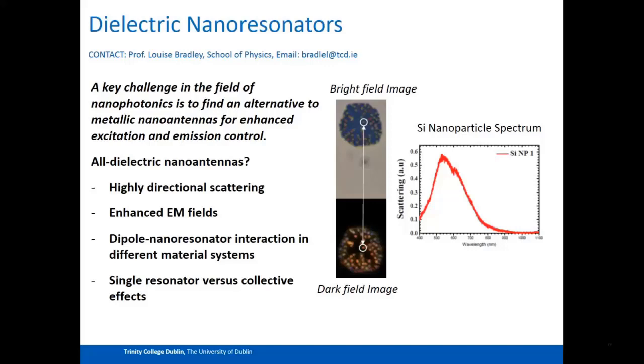Using that dark field microscope that I showed you earlier, these are lots of silicon nanoparticles, and you can see that if we look at it in the bright field microscope, it looks green. If we look at it in a dark field microscope, it looks red. So they have the properties to directionally scatter light of different colors in different directions. And again, we want to see, if you couple this with something, can you make it into a dynamic resonator? Are you able to change the properties of emitters, to change their relaxation pathways depending on how you actually control it?